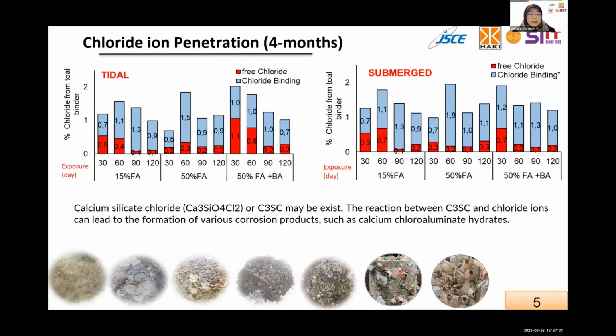We found that the binding capacity of concrete containing fly ash is still very good, but it is greatly improved when high volume fly ash and biomass is applied. We predict that the calcium silicate chloride, often referred as C3SC, maybe exists as a chloride bound with the decomposed calcium.